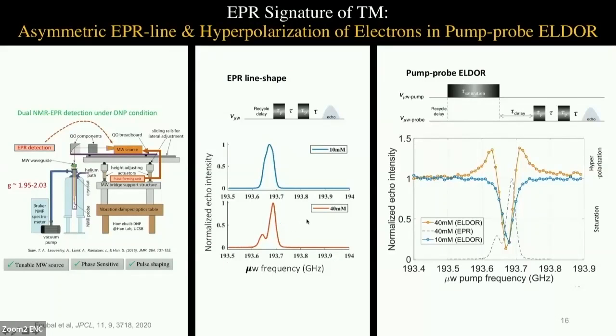What is even more interesting in our EPR finding is that the systems that give rise to thermal mixing DNP, when we perform ELDOR experiments, which is a pump-probe experiment where we first saturate a portion of the EPR line and see how that saturation affects a certain select probe frequency, we found that for systems which give rise to thermal mixing, we have these humps. Normally, we would have expected only a saturation or the flat line, but here we have these humps coming up in systems that give rise to thermal mixing DNP.